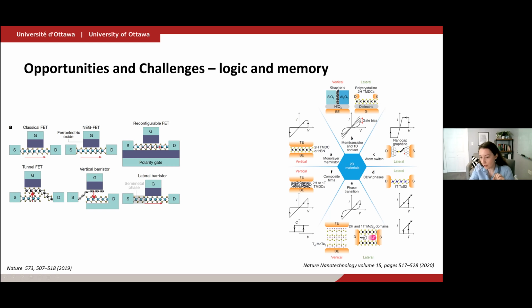More interesting are also the ones that have to do with different phases of these 2D materials. So, for example, the charge density wave phase in 1T tantalum disulfide can go from one type to another, and that comes with a huge change in resistance, orders of magnitude. And so the appearance of the charge density wave upon application of electric field, for example, or temperature, can be controlled and can be used as a memristor, as a switch as well.